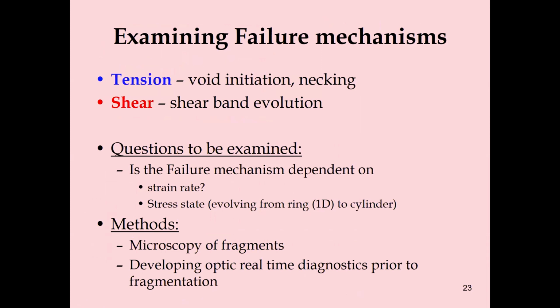So examining the second stage, we're looking at failure mechanisms as we're looking at these fragmented cylinders which are soft-catched. We could look at different failure mechanisms. In general, we could look at tension and shear. Tension, we're looking at, of course, under the instability of necking and void initiation, and on the other hand, the evolution of shear bands. And one of the questions we wanted to examine is, is the failure mechanism dependent on strain rate, on the stress state? For instance, we could look at specimens evolving from 1D behavior from a ring over to a cylinder.